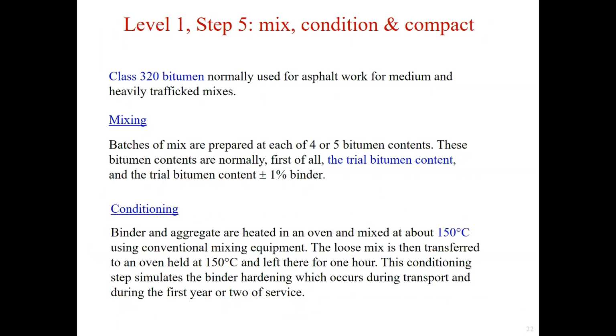Once the trial binder content is chosen, we start to mix, then condition and compact the asphalt mix in step 5. We need to ensure the sample prepared in the lab has properties as close as possible to asphalt placed in the road, and this is an important aim of the asphalt mix design procedure.